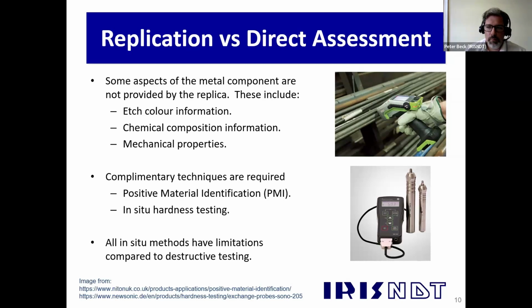And then lastly, the mechanical properties of the material. Again, obviously it's an acetate replica, so they're not transferred. So this is where we'd use portable hardness testing. So the bottom image there is of a UCI type hardness tester, which gives essentially like a Vickers hardness equivalent to about HV5. So from that, we can get most of the information from a material to support the replication technique. I suppose all portable equipment has considerable limitations compared to static equipment, and in an ideal world we'd do destructive testing, so we would do a proper tensile test and things like that. These techniques will always have much greater uncertainties. So you'd have to already have some idea of what the material is that you're testing. And then it's more about saying, yes, this is the correct material properties, and they match to the grade that you expect.